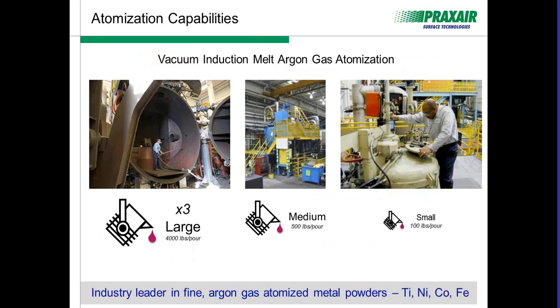We have a medium-sized atomizer built for pilot scale as we ramp up from our developmental atomizer, which pours about 100 pounds per heat. We like to use that methodology when we work with our customers, from testing and developing to pilot stage, and then ramping up to hundreds of thousands of pounds on our large atomizers. In general, this fleet of atomizers can pour in excess of 4 million pounds of liquid annually.